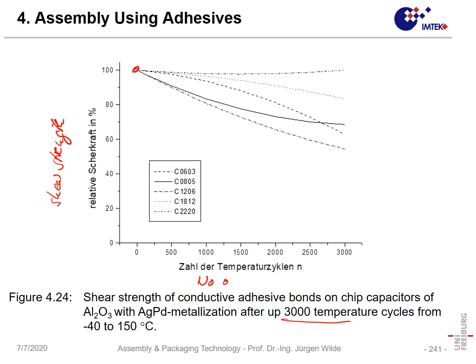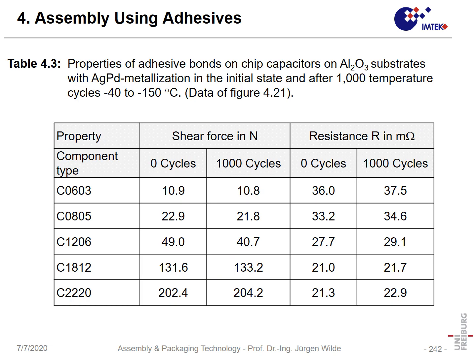Here on the x-axis is the number of cycles n. What is also interesting is that this maximum decrease is not for the biggest and not for the smallest devices, but for some intermediate size. Here that's a 1206 we have. But generally it means that up to 3,000 cycles we still retain a large shear strength, and that means we can build very reliable circuits which also can withstand high operating temperatures.